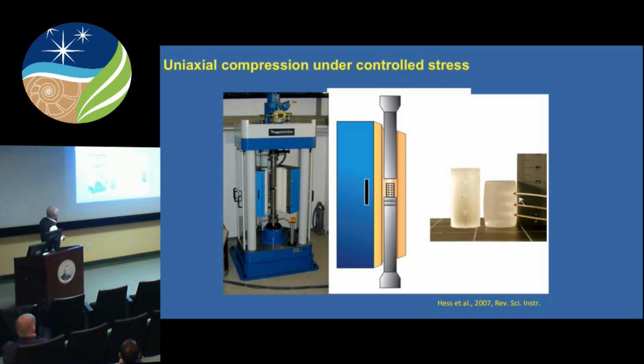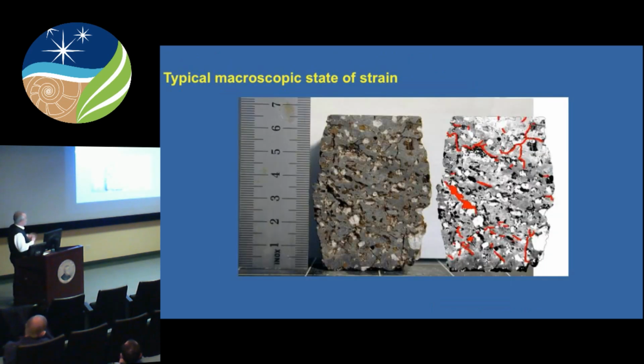and I'll just give you examples of one or two of them. We've measured the viscous heating in the system by taking an initial cylindrical sample. In this case, it is standard material, an NBS standard glass. I don't think anybody has used this much at one time before. And then deforming it in a uniaxial press, as you see on the left. So you see a slightly barreled sample, very nice and homogeneous, symmetric around its midpoint, which means you have a nice temperature field. It's not distorted.